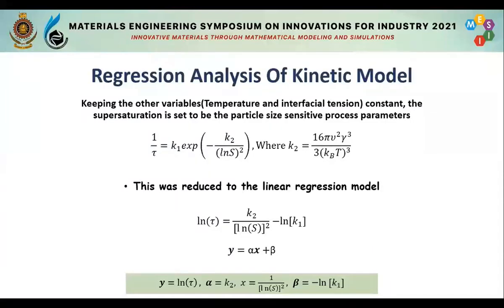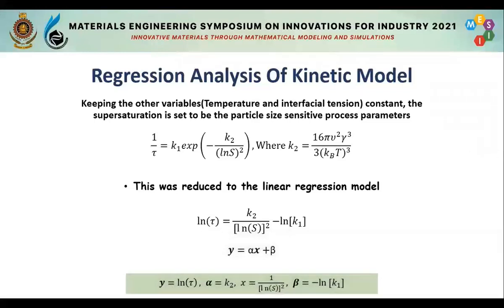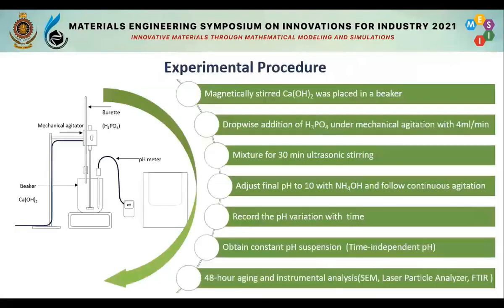Actually, we made a regression analysis, which is nonlinear for the kinetic model, with some regression constants like K1 and K2. Then we reduced that nonlinear regression model to a linear regression model with some mathematics. Then we needed to calculate K1 and K2 as our regression constants.